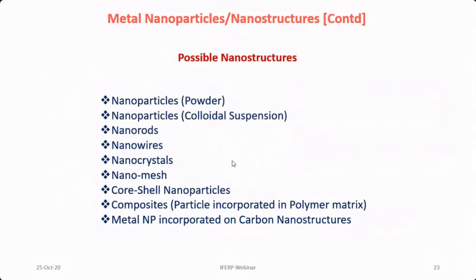One more thing I wanted to add: when we see all these possible nanostructures with the naked eye, the nanoparticles in dry form look like a powder only. If you touch it, it will be very fine, and we should not touch it with bare hands because they can penetrate through our skin also. But they are very tiny, so if they are spread in a very small concentration into any liquid, they are suspended, and you won't even see them inside; it will look like a clear solution. Many times people mistake it as a solution, but nanoparticles never form a solution, they form a suspension. Even though it is clear, when you put it in the right instrument or appropriate technique, it can be differentiated by scattering and diffraction.